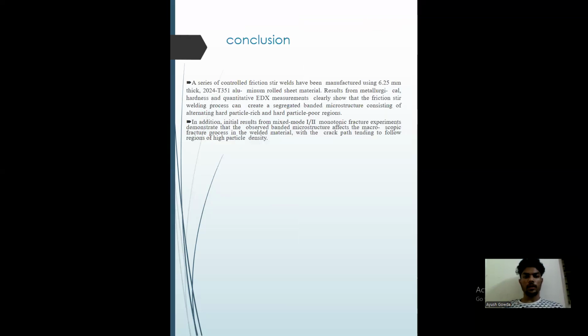Conclusion. A series of controlled friction stir welds have been manufactured using 6.25 mm thick 2024-T351 aluminum rolled sheet material. Results from metallurgical, hardness and quantitative EDX measurements clearly show that the friction stir welding process can create a segregated banded microstructure consisting of alternating hard particle-rich and hard particle-poor regions. In addition, initial results from mixed mode I-II monotonic fracture experiments demonstrate that the observed banded microstructure affects the macroscopic fracture process in the welded material, with the crack path tending to follow the regions of high particle density.